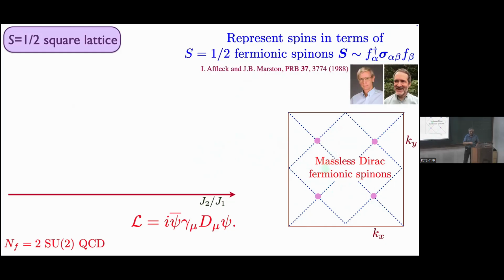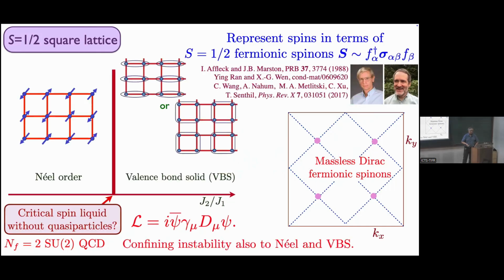But the formulation of that critical spin liquid that I'm going to use goes back to Affleck and Marston, even before us, where they wrote the spin in terms of fermionic spinons. And there's a particular mean field theory that's mentioned in their paper, which has 4 massless Dirac spinons at these points. So this looks very, very different from the CP1 theory, but wait on that a minute. You can also look at fluctuations about these massless Dirac fermionic spinons, and it turns out a very simple theory. It's just like our theory of strong interactions of massless quarks. There's 2 quarks, and it's not SU(3) quantum chromodynamics, it's SU(2). And this was, I think, already known to Ian Affleck, certainly even at that early time. But since then, there's been a lot of work trying to analyze the fate of this QCD theory. And it has 2 possible fates. One is that there's a critical conformal field theory. The other is it confines.